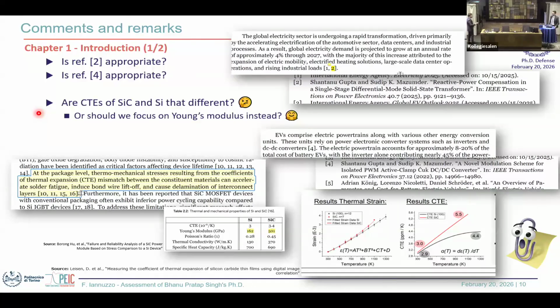So basically, silicon carbide is much tougher because it has a very high Young's modulus. We can say we have one soft material and one hard material. So even though the mismatch is not that different, when the solder layer stretches because of the thermal expansion, silicon carbide will have a higher impact on the solder layer, which will eventually result in much higher strain accumulation because of the very high Young's modulus. In case of silicon, it's a bit softer. So that's why we also observe that if we use the same technology. But that's because of Young's modulus.